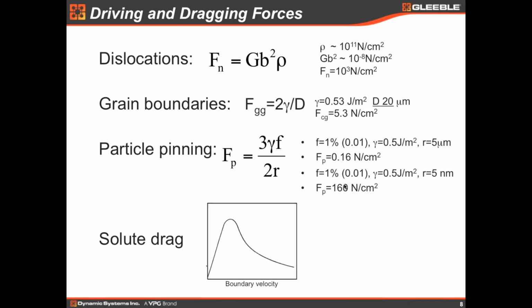And finally, the solute drag. We have here solute drag acting in the grain boundary. It's a kind of complex, because you can treat solute atoms as particles in the beginning, but the only difference is that they can follow the grain boundary by diffusion. So I think this is the best way to explain that. At low grain boundary velocities, for example grain growth, there's a small driving force, so the grain boundaries move slowly. So the solute atoms can actually follow the grain boundary by diffusion.